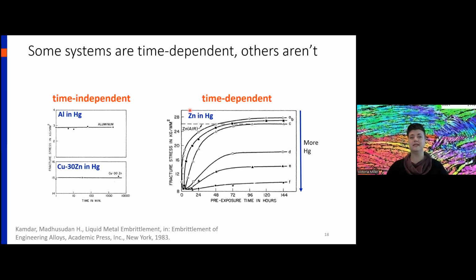Whereas when you expose zinc to mercury and varying amounts of mercury, the fracture stress is very sensitive to the pre-exposure time. So some systems are time dependent, some are time independent, some get better with prior strain, some get worse with prior strain. A lot of contradictions in the literature.